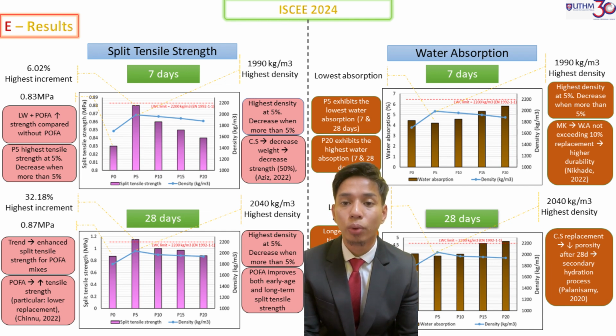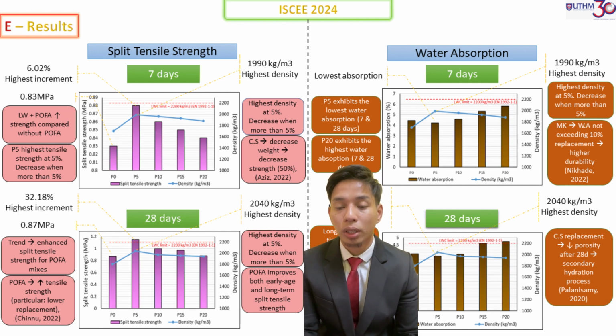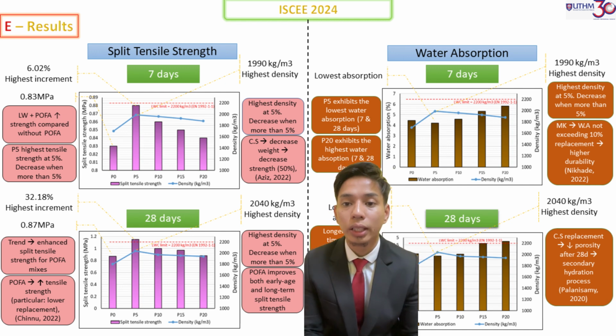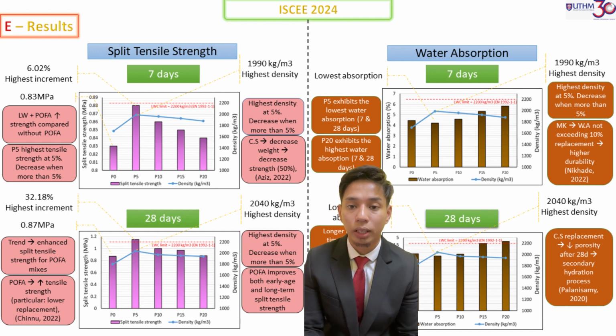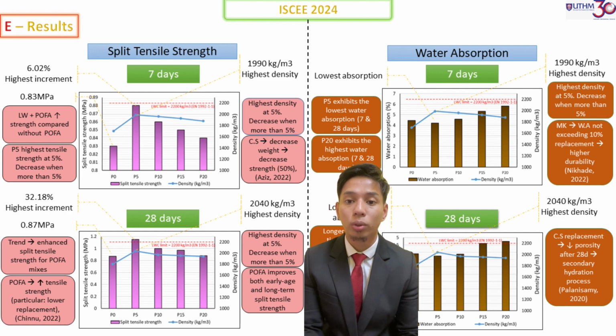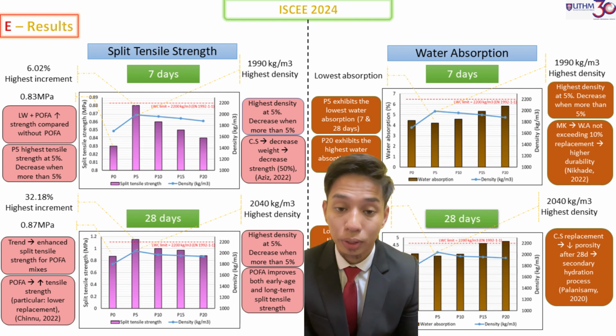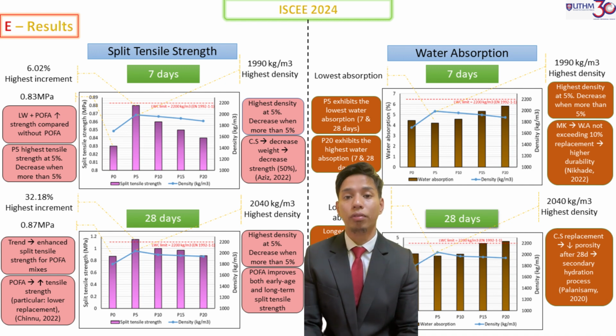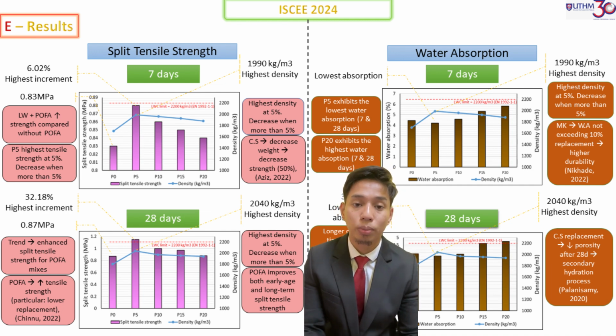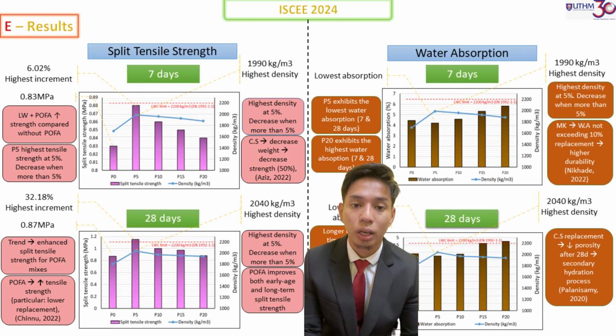which is a 32.18% increment from the P0. So the trend is enhanced split tensile strength for POFA mixes. So using POFA in the lightweight concrete will increase the tensile strength, particularly at the lower replacement, which is 5% of POFA. The density is also highest at P5 for 28 days. POFA will improve both the early and long-term split tensile strength.